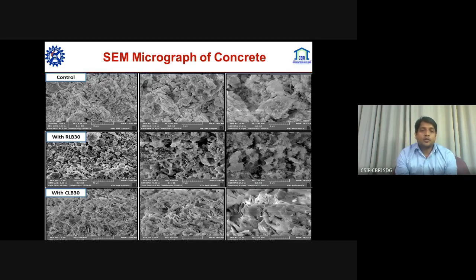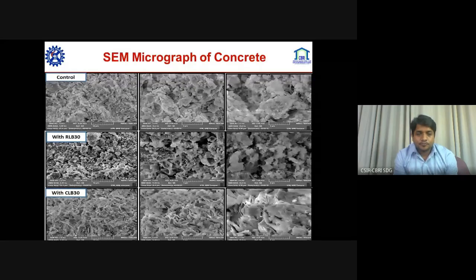Further, in the SEM micrograph of concrete with the raw lime sludge based binder, it can be seen that the lime sludge is scattered and not compact and uniform, while in the calcined lime sludge based binder, the SEM micrograph was more uniform and compact.